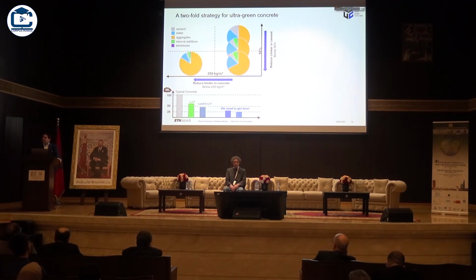But if we move in the other direction, and we now look at reducing the amount of binder in the system, the amount of cement paste per cubic meter, is when we can really move and transition from a typical concrete with 100 units of CO2, if you want, to something that has virtually a quarter of the CO2 of the original mix.